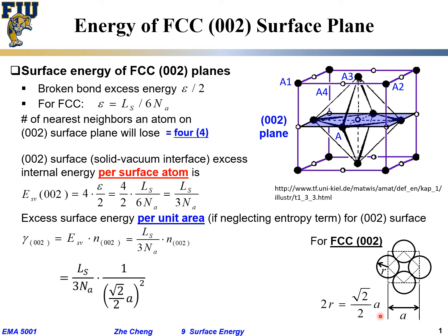Now in this case, how do we estimate N? We keep the first term for the excess energy per atom, and then N. If I'm looking at this small square, this dashed small square, how many atoms within this dashed small square? Here is one quarter. One, two, three, four, totally gives me one. And what's the edge length for this small square? It's 2R. And what is 2R? 2R is square root of 2 over 2 times A. So that's our area density. And of course we can work out the math to be 0.67 times Ls over Na A squared.